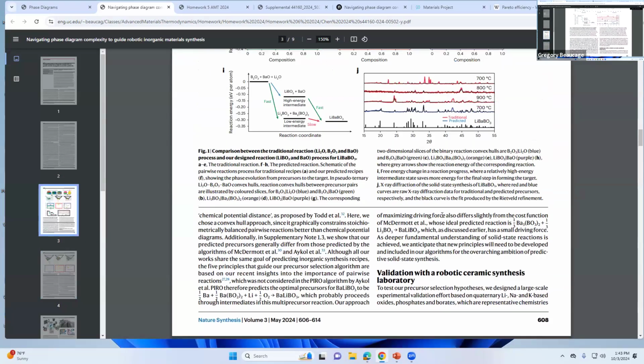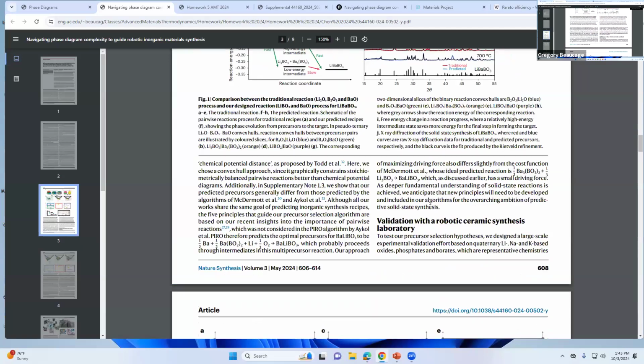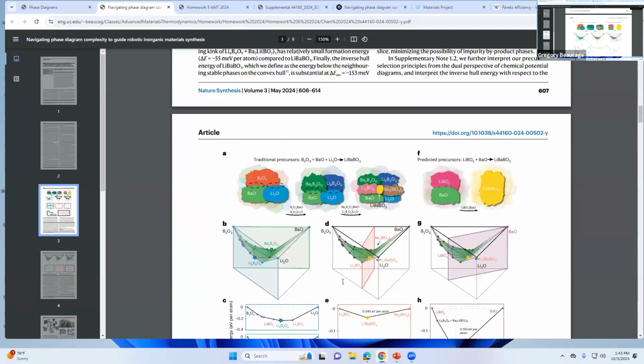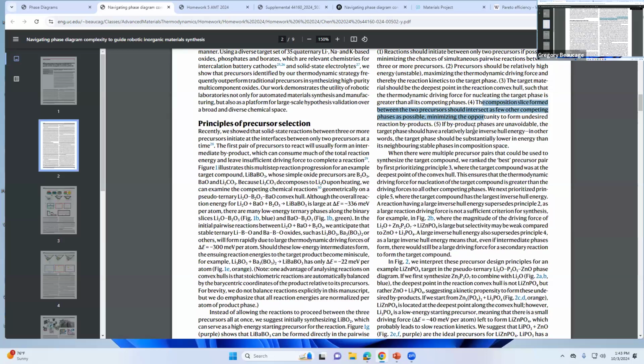So if you have competing phases, or even when it's weak, a neighboring phase, like the orange phase, would have almost the same driving force. That means when you try to make the yellow, the orange is going to form at 50% of it. So you'd have a large impurity in it. It wouldn't work out. So they all kind of make sense. The only thing that might not make sense is that binary is the only way things can happen. And then if you do have byproduct phases in the pathway, then you should have a lower energy in the byproduct phases.